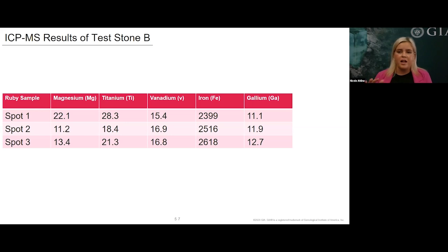So here we have our ICP chemical analysis of the stone. We look at 5 elements that are a little bit different from our emerald: magnesium, titanium, vanadium, iron, and gallium. Now, when we run a stone for ICP and it is a corundum, we also look at our titanium and beryllium content to assist with the titanium-beryllium diffusion call. This stone was heated at high temperatures, so let's check out what our beryllium looks like.